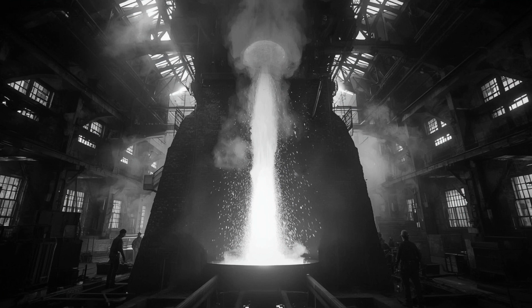On the right side, the opposite problem develops. The iron comes fast and hot, almost aggressively. The first rush from the tap hole carries so much thermal energy that the clay plug sometimes fractures instead of drilling clean. The runners glow white at the edges. Slag separates violently, spitting and steaming when it hits the cinder pit. The crew learns to stand farther back to anticipate the surge.